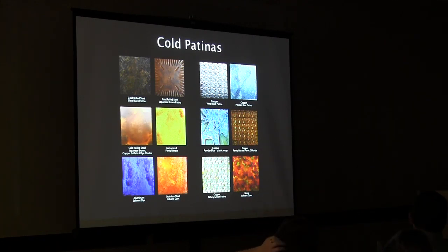Flaking generally comes on a metal, I don't care what metal. When you put the patina on, you don't think it's working very well, and you let it sit for 10 or 15 minutes, and then you put the patina on again. What happens is that second patina starts undermining the first one. It's trying to graft to whatever the metal is.